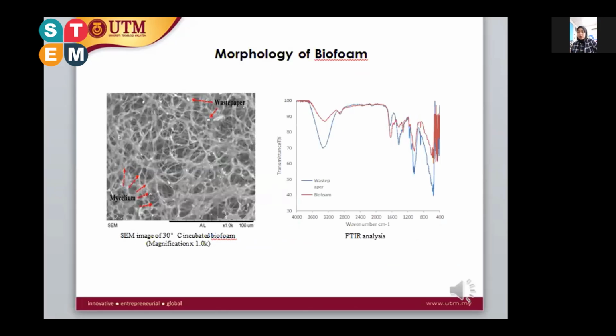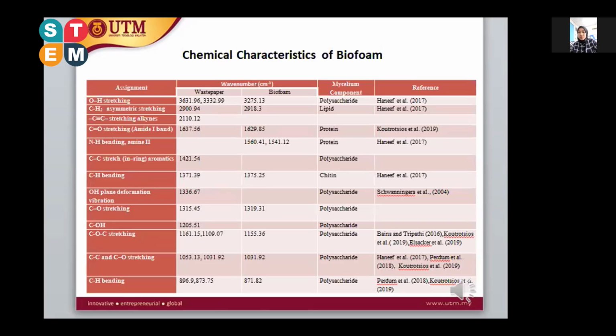Okay. So here is the morphology of the biofoam. It shows an internal structure of the mycelium in the biofoam that we observed using scanning electron microscopy analysis. It shows the morphology of the 30 degree incubated biofoam, and the mycelium spread widely on the waste paper. The FTIR result also indicates that the mycelium biofoam has significant absorption on those scattered bands. Here is the broad absorption peak that indicates the presence of the OH group and shows a typical carbohydrate pattern in FTIR analysis. A summary of the bands with assignments is listed in this table, and it shows that the mycelium bioform mainly consists of polysaccharide, protein, and also lipid.